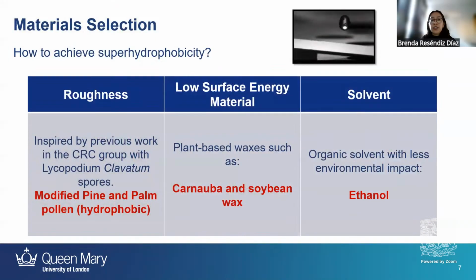So for the material selection, how can we achieve this system? I was inspired by the previous work of my research group, where one of my colleagues, Dr. Emma Sadler, used Lycopodium clavatum spores. So I was looking for other pollens and other methodology where I can modify it to turn it hydrophobic. So I modified pine and palm pollen species. Then for the low surface energy material, I used two different types of plant-based waxes, carnauba and soybean wax. And for a solvent with lower environmental impact, in this case, I use ethanol.